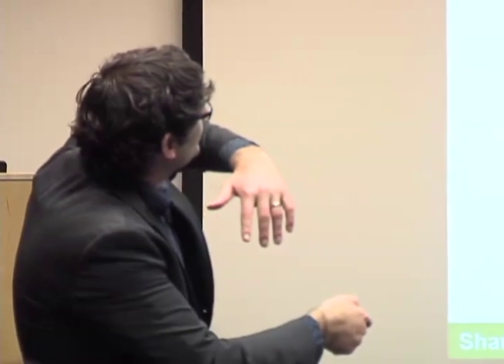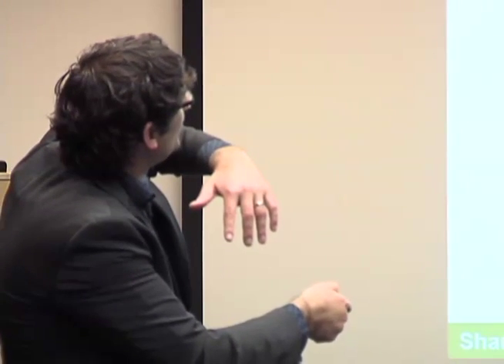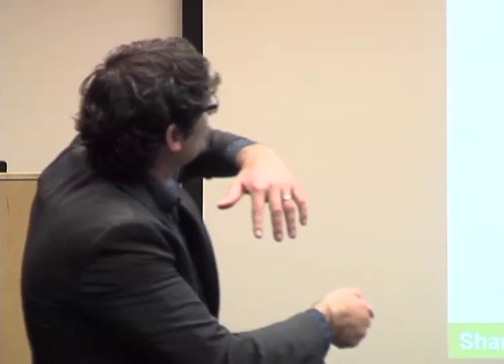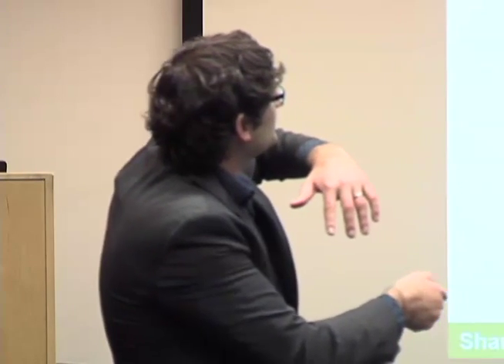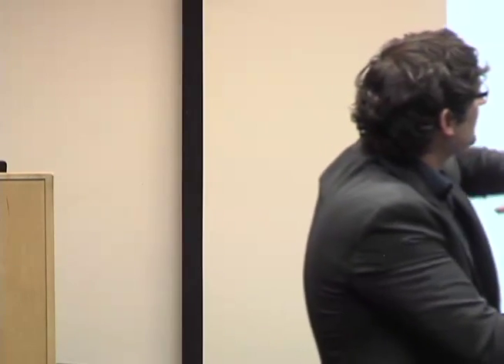So we looked at the electronic conductivity. And so this is a very simple but neat experiment. We take an interdigitated electrode, and it's a bipotentiostat experiment. So what we do is we have an interdigitated electrode array with these gold fingers. We deposit a catalyst film on top of it. This is dried out. That's why it's breaking up into pieces.